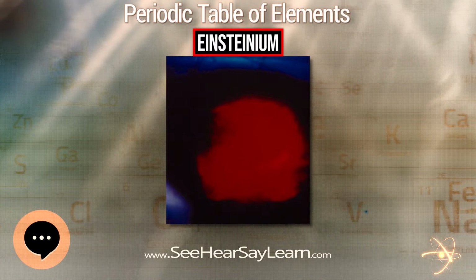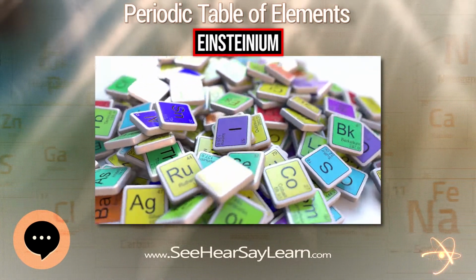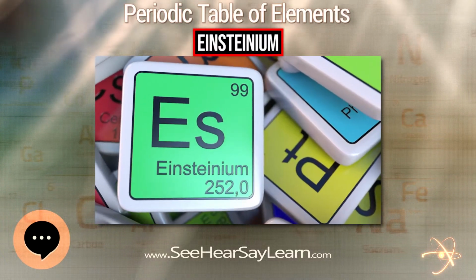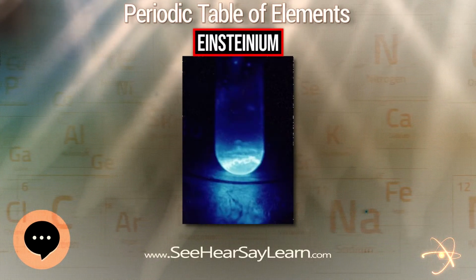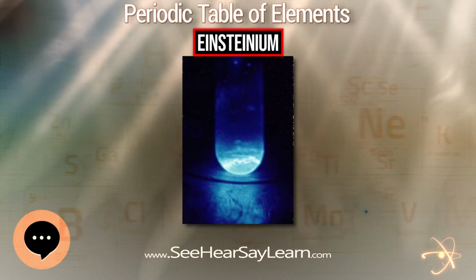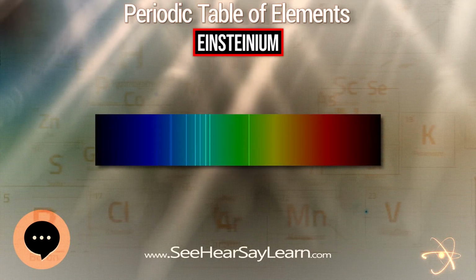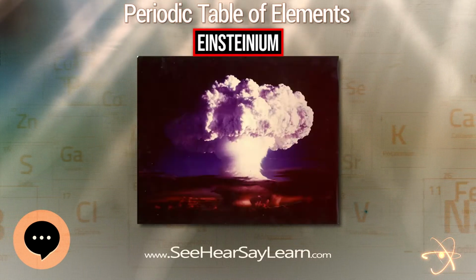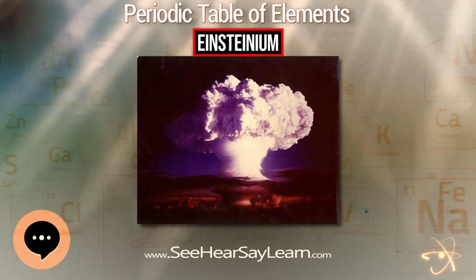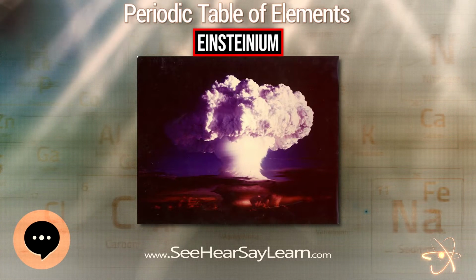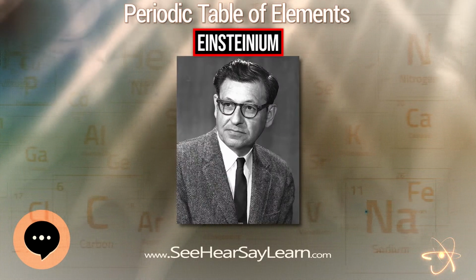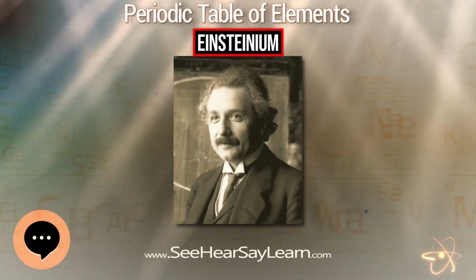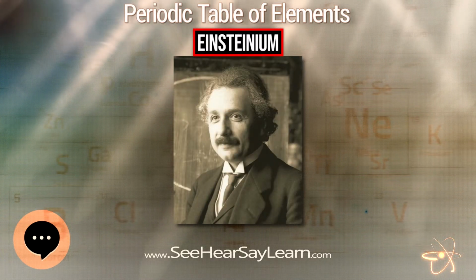This allowed reducing the radiation damage so that the compounds did not disintegrate during the period of 20 minutes required for the measurements. The resulting luminescence from Es3+ was much too weak to be detected. This was explained by the unfavorable relative energies of the individual constituents of the compound that hindered efficient energy transfer from the chelate matrix to Es3+ ions. Similar conclusion was drawn for other actinides: americium, berkelium, and fermium.